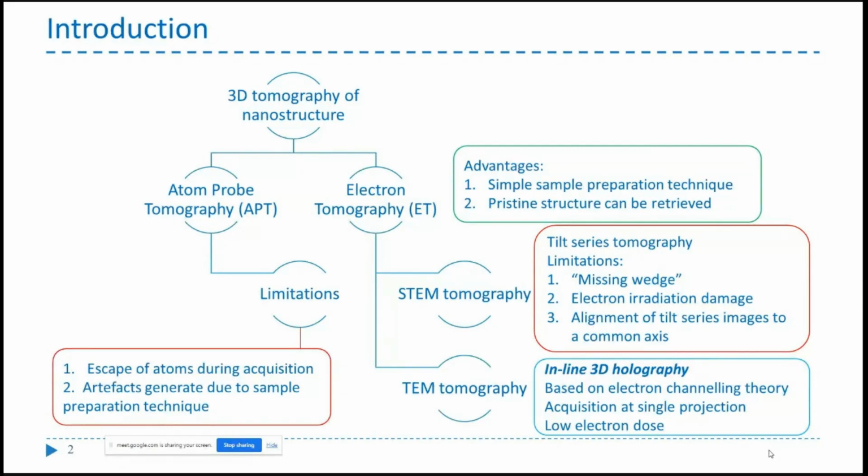What is TEM tomography? You take images from one projection, you take an image at different defocus, and from that you can determine the 3D structure. And interestingly, I will show that you can go up to 0.4 angstrom resolution in the Z direction. So sub-pico, 40 picometer resolution you can achieve there. Actually, we achieved that, so we will show that.